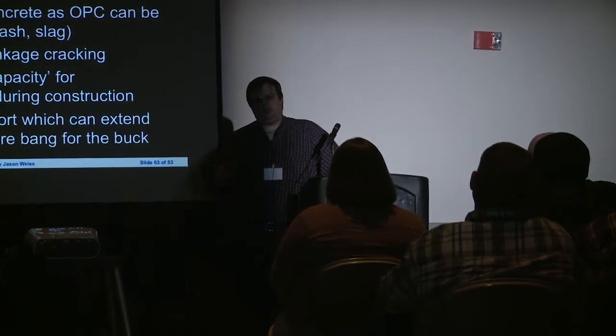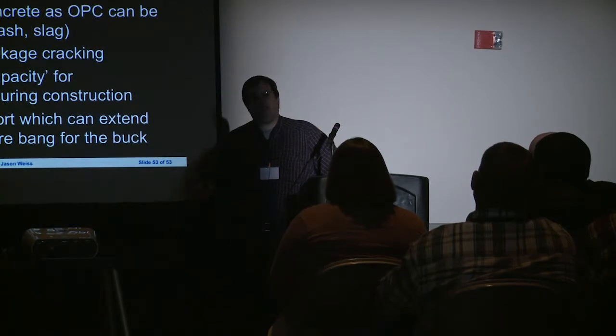It's cementitious, and what I would point out there is, while we know that there's a chemical shrinkage that occurs with the cement, it's higher for fly ash. It's about twice as high for fly ash. Slag, it's about 4 times higher, when you get to silica fume. All right, so there's a little bit of an adjustment that goes into that, but you essentially are replacing it